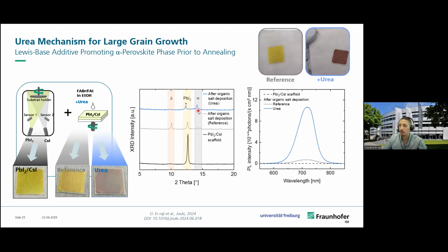And this gave us reasons to believe that besides the crystallization that takes place, due to the fact that urea cannot really take part in the crystal structure, it is expelled to the perovskite surface. And as we know, when we have perovskite in proximity to C60, it leads to the creation of in-gap states where charge carriers can be trapped. And if we have enough distance between the charge transport layer and the perovskite absorber, we can eliminate these states. And this is what we think urea does. So it leads to the local separation between the perovskite and the C60, which then minimizes non-radiative recombination, as we have seen in PL measurements.